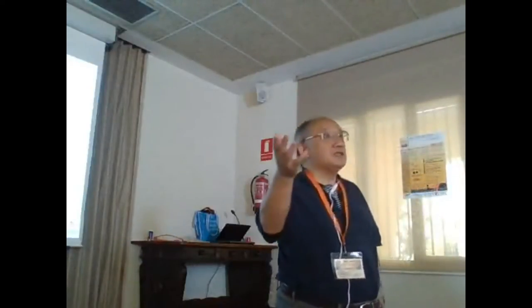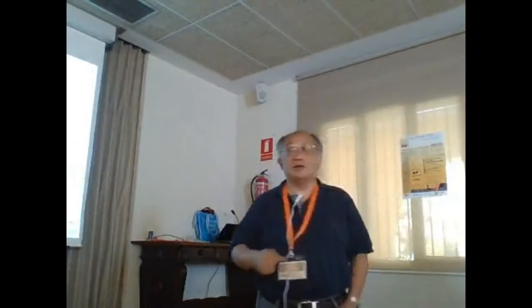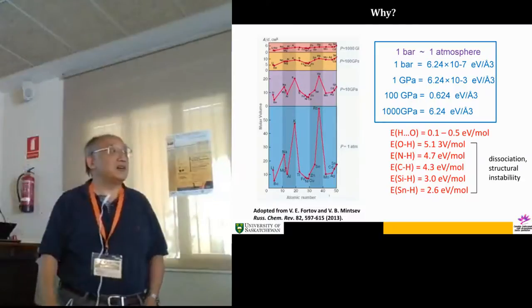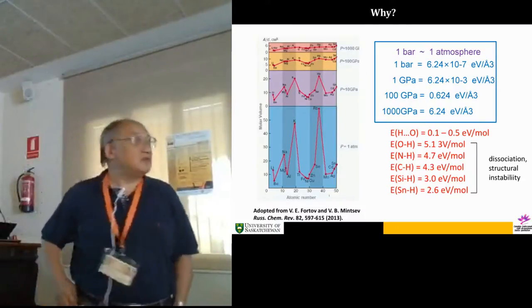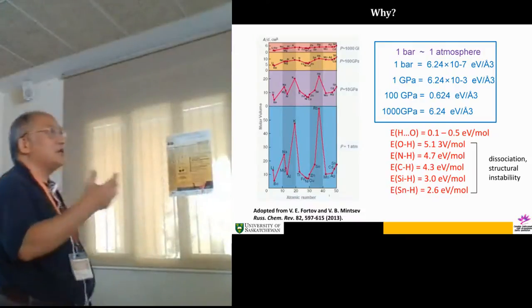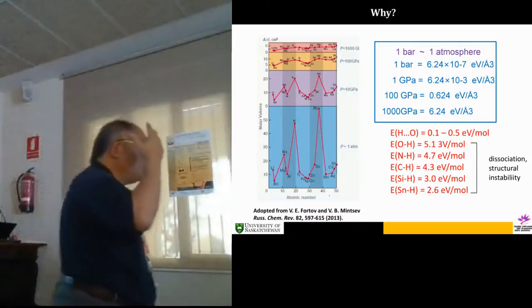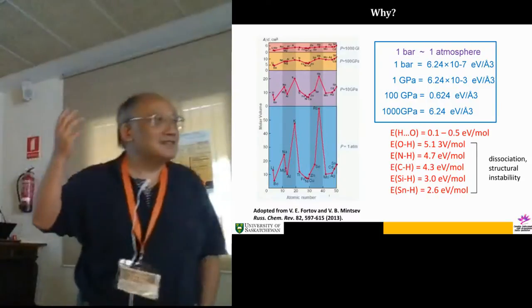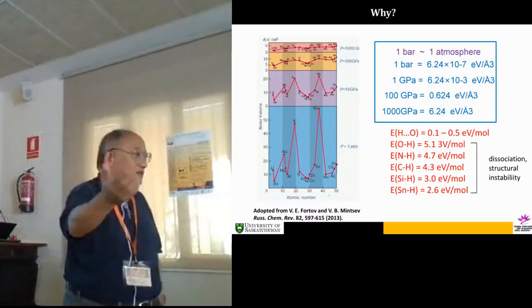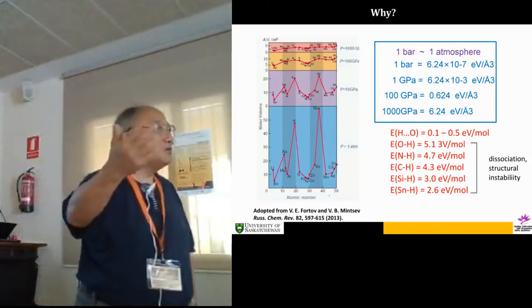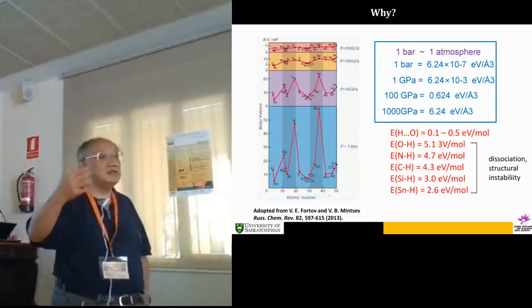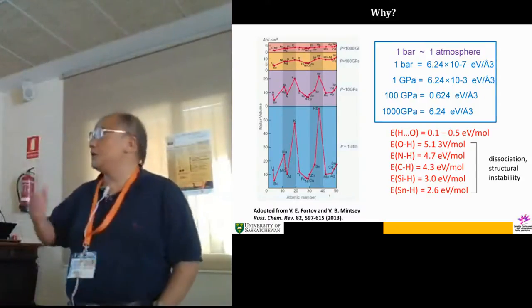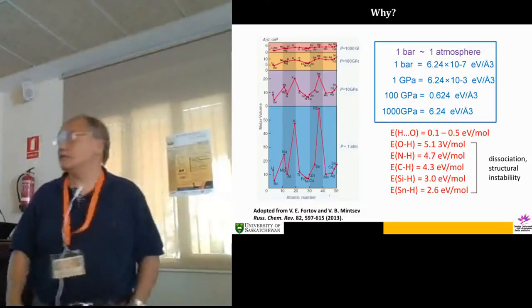So if you're a good chemist, look at the periodic table. You can predict properties because of the periodic trend of the size of the atom and the number of electrons the atom carries. When you compress it to 1 terapascal, 1,000 GPa, there's absolutely no difference. So that's why you put any metals and you compress them, you get new funny structures. And that's why the heydays of the late 1990s to 2005, when people started using really high resolution synchrotron radiation and could achieve a pressure much higher than 50 GPa, you could get very nice and very surprising results.